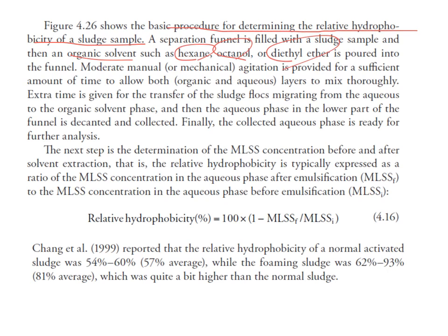Before and after the extraction, we compared the MLSS concentration, and the relative hydrophobicity can be quantified using this equation. So we can just take the ratio between before and after emulsification using this organic solvent.